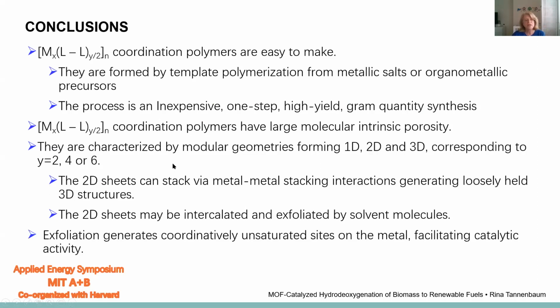They're characterized by modular geometries. We can have 1D, 2D, 3D, corresponding to Y equals 2, 4, or 6 here. And the 2D sheets stack via metal-metal stacking interactions, and they generate these loosely held 3D structures that are very labile. The coordination bond is weak, and so it is very easy to intercalate the substrate at not very high pressures. And so the 2D sheets may be intercalated and exfoliated by solvent molecules, and of course, the substrate. And so this exfoliation generates coordinatively unsaturated sites on the metal that facilitate the catalytic activity.